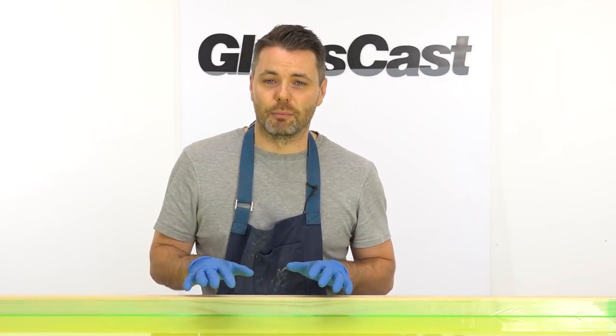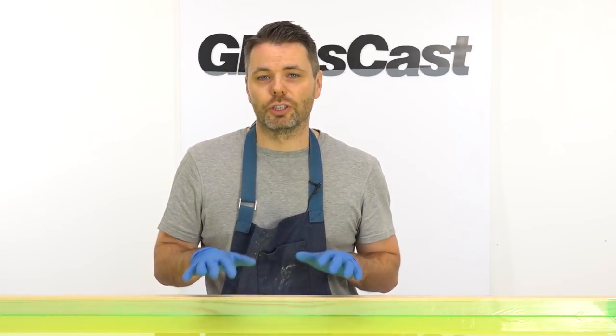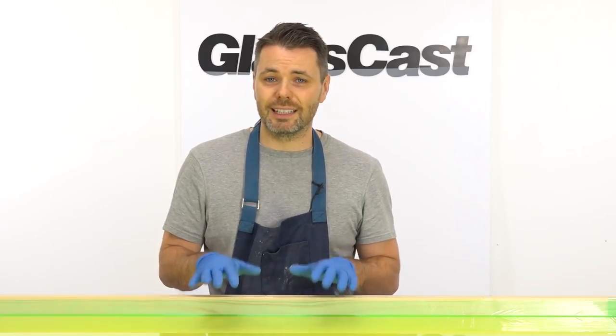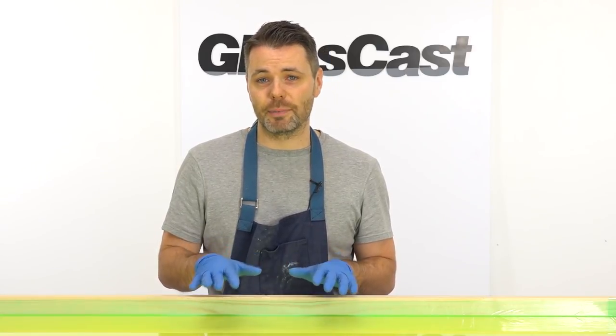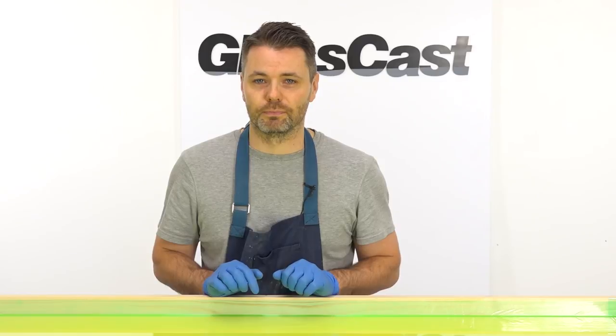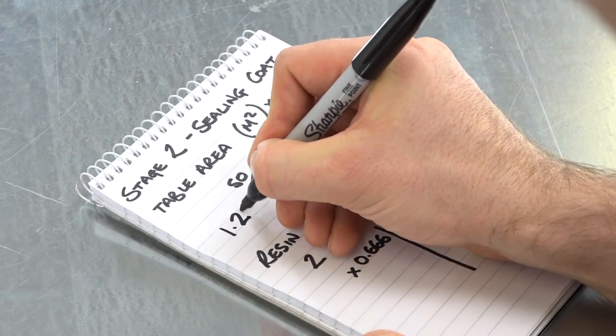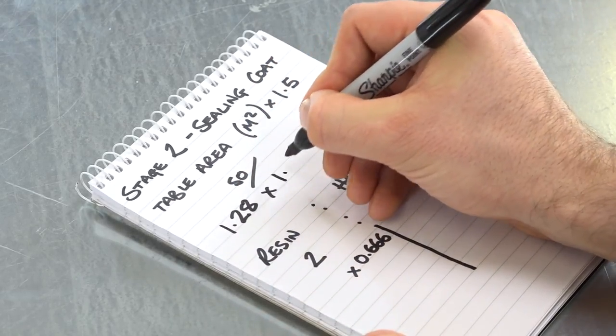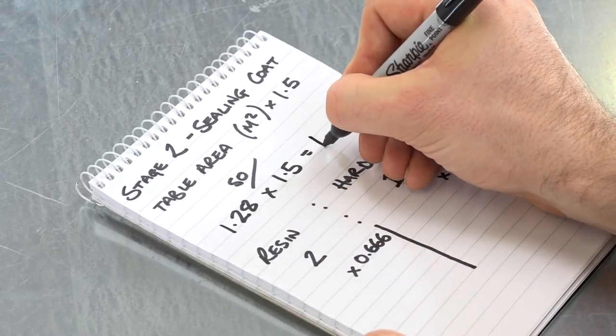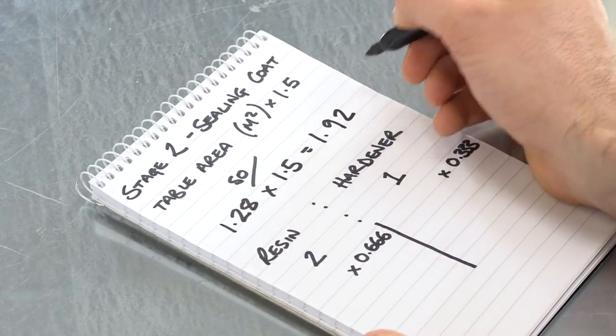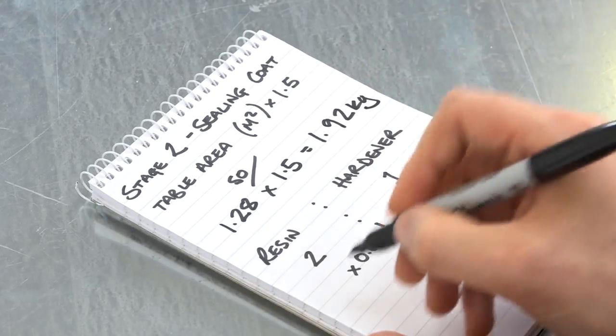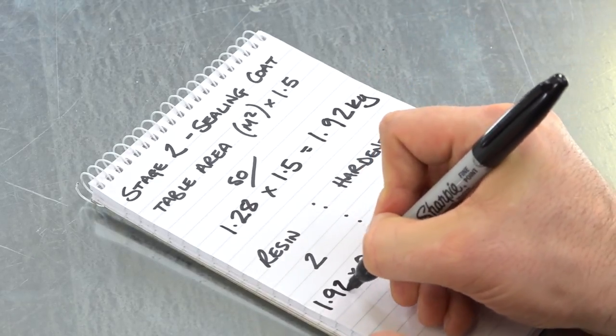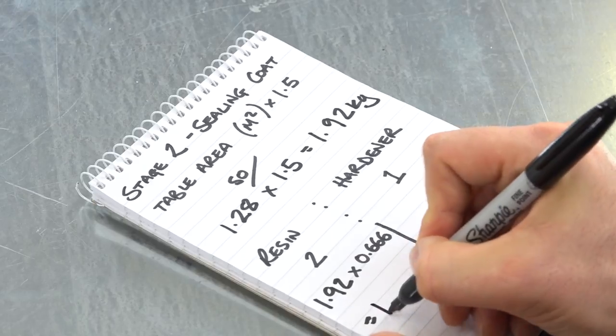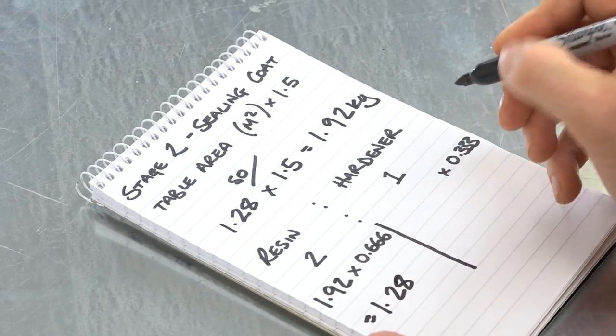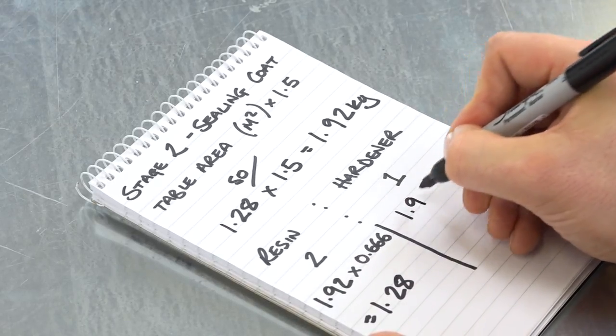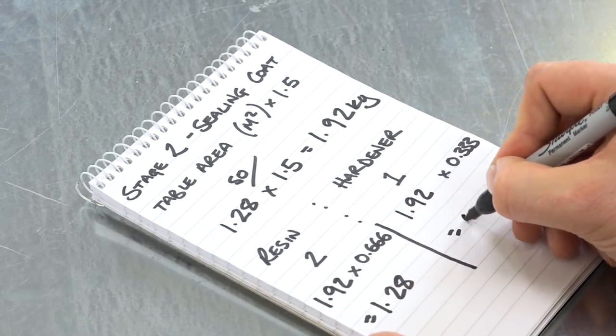The purpose of this second pour is to seat the planks down onto the base layer and also to fully seal the planks to prevent air from escaping from the wood during the later pours. The amount of resin needed for this second stage is 1.5 kilograms per square meter. From earlier, we know we have a 1.28 square meter table, so 1.28 times by 1.5 equals 1.92 kilograms. Splitting this amount at the 2-to-1 ratio, this gives us 1.28 kilograms of resin and 0.64 kilograms of hardener.